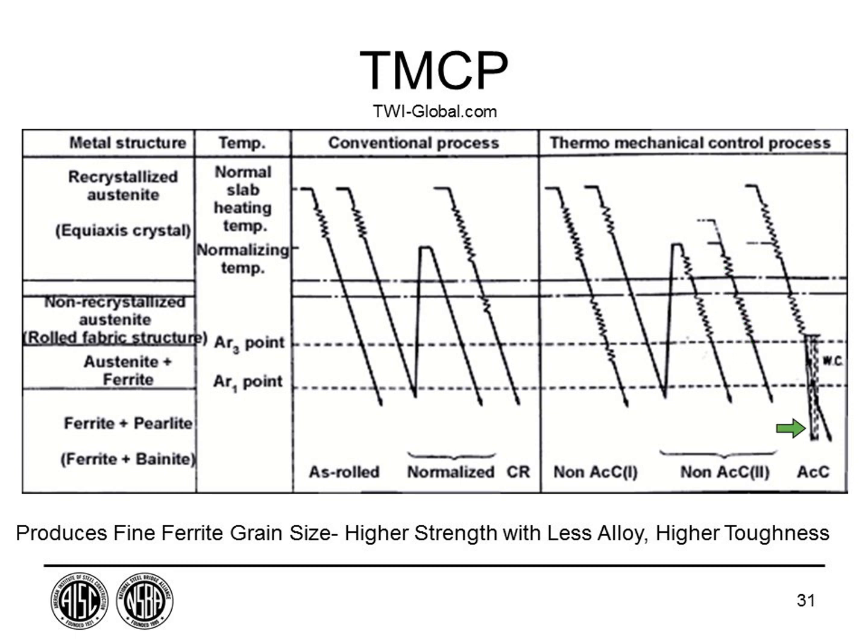Then you can do something else that's sort of interesting: you'll do some rolling up here, some rolling here, and then cool it quickly down in this range. This is not to form martensite, it's just to accelerate the cooling to give a better grain structure. This is done in some of the jumbo shapes. If you know about the issues with the properties at the k-region of a jumbo shape, this is how some producers improve those properties. They cool that area locally to get better properties out of it.